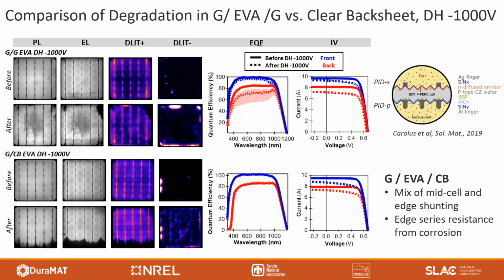This PID polarization has been seen by others, and it is more specific to the glass-glass structure, where sodium ions diffuse toward the backside of the cell from the rear side glass. The positive ions then counteract the quality of field effect passivation from rear side layers like aluminum oxide.